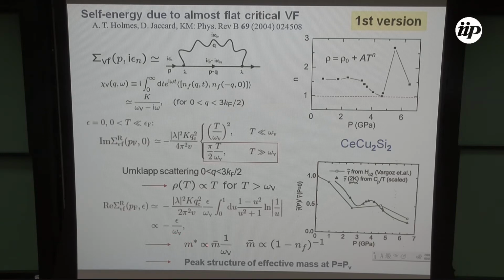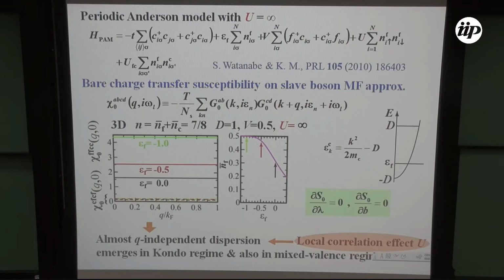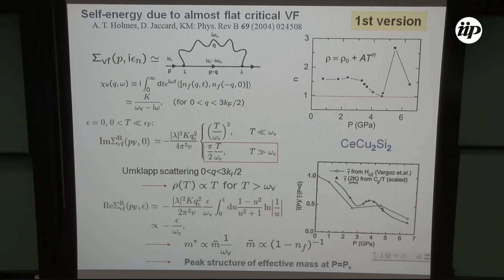M star over M is given by the so-called Brinkman-Rice expression times the enhancement. So near the critical pressure, M bar decreases rapidly, but this effect shows some structure here. So in this sense, the series of anomalous properties observed in CeCu2Si2 and CeCu2Ge2 under high pressure can be explained by the so-called critical valence transition or fluctuation phenomena.